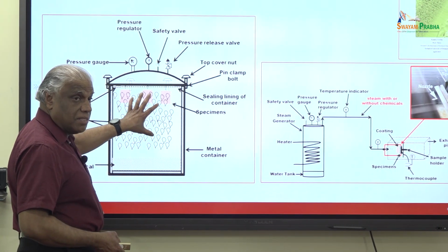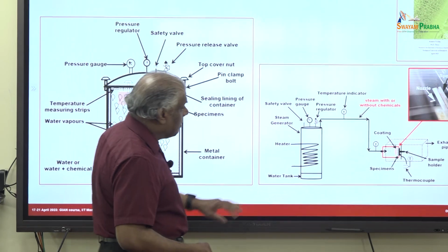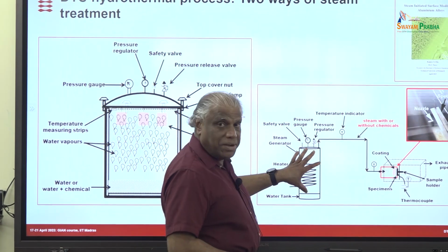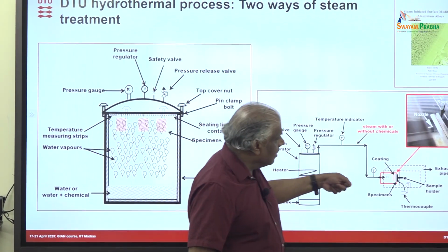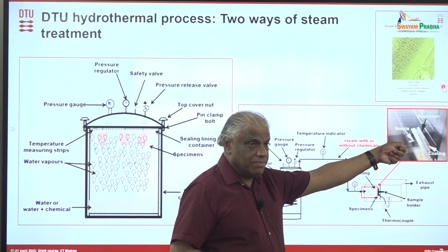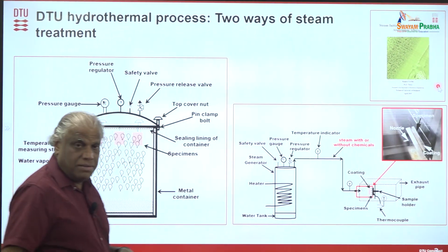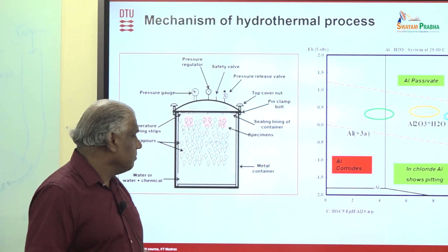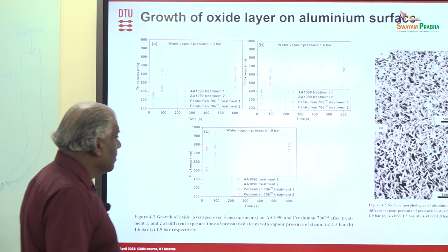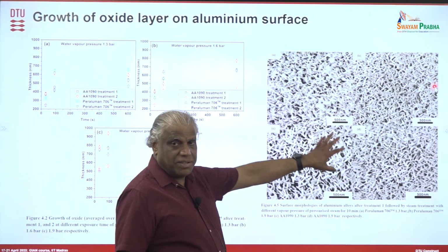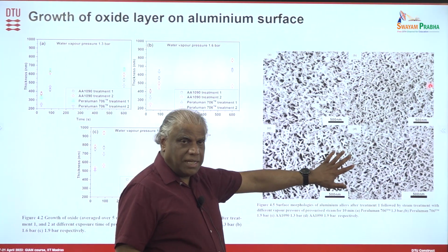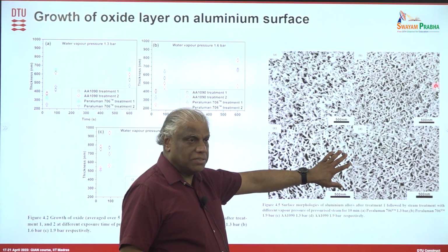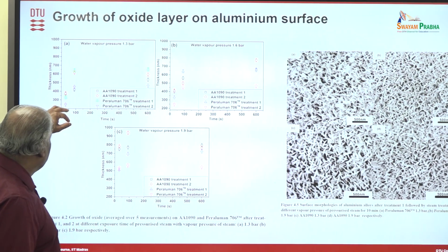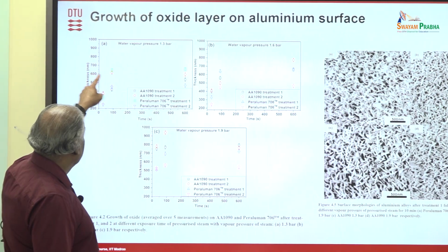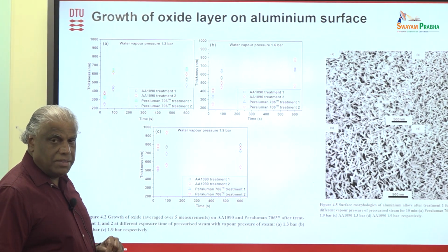This is like a batch process. You have to put it inside the cooker, but you can also make a high pressure, high temperature steam and then spray it onto the surface. So you get a similar effect as this one, and that way you can form the coating. So you get this kind of nice coating on the surface. This is the aluminum oxide, the naturally formed aluminum oxide, which we thickened. You can see that with a steam treatment of 1.3 bar, we can go up to 600 nanometer thickness.